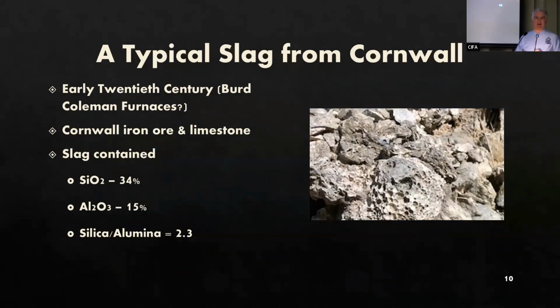Now, to illustrate better the typical slag from Cornwall, I put on this slide the composition of a piece of slag that probably came from the Burd Coleman furnaces. The Burd Coleman furnaces right here in Cornwall used limestone from Cornwall as well as the iron ore from Cornwall. And the fuel that they used was anthracite coal. And you can see that the silica content of this slag is about 34%, the alumina content about 15%. And so the ratio of silica to alumina is 2.3, and that's about typical for an iron blast furnace slag. You can see some of that slag over on the right-hand part of your screen from the Burd Coleman furnace.